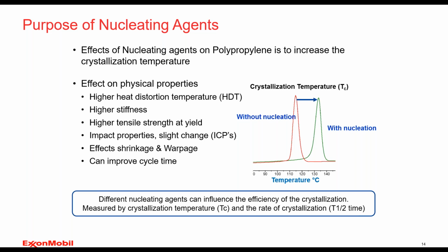So about nucleators. Nucleating agents, there's different types of nucleating agents. Some are more powerful than others, but the end result is that a nucleator will change the crystallinity of the polypropylene, and when that crystallinity changes, you're improving different aspects of that polymer structure. You're going to offer higher heat resistance, you're going to offer higher stiffness, higher tensile properties. There's other properties that go hand in hand that could be considered like the hardness, the surface hardness of the resin. Very beneficial. And in an ICP, the beauty is that those nucleating agents will not affect or have very, very little effect on the actual impact properties. Where they do have a significant effect is in the dimensional shrinkage or warpage of the part.